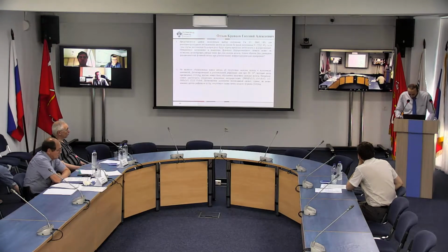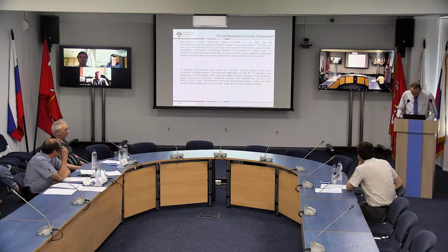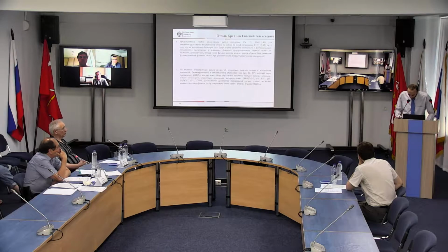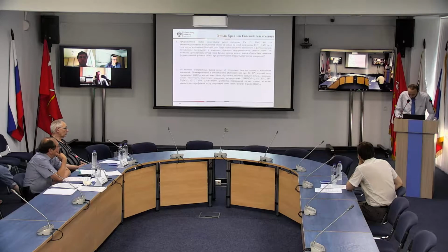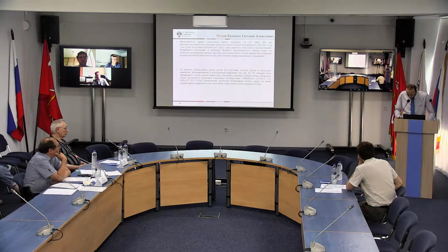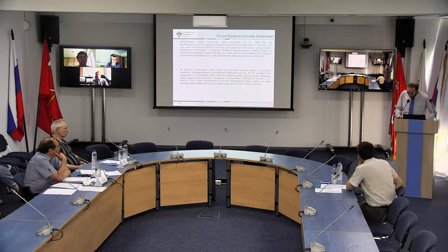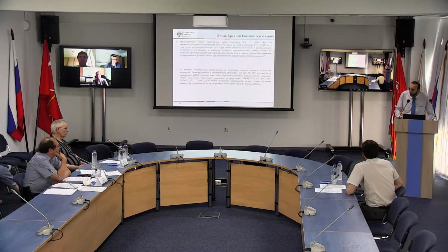Regarding the first comment about the background and absorption due to the copper tube, yes, I agree with you that if we used cobalt radiation for our sample, it would suppress such noise. However, fortunately, a high energy resolution detector used in our system can distinguish and exclude the sample fluorescence, thus greatly reducing the background. This for the first comment. And about the second comment